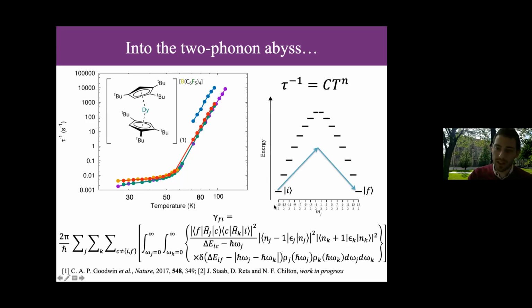And so here I'm just drawing a sketch that I like to give my undergraduates for how this process works, because you don't draw arrows directly between states anymore, because this transition is a simultaneous absorption and emission process of 2 different phonons. And you never transit via a real excited state. So drawing these arrows going to any real state here is not true. And so this here is the expression, or one of the expressions, for the relaxation rate in a 2-phonon process.